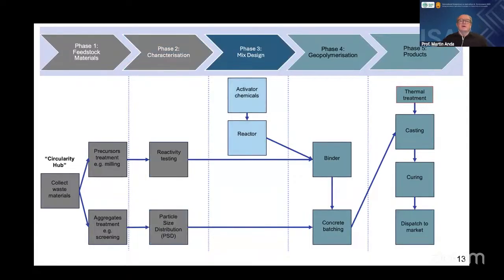Once we've done that, we can go into phase 3, which is developing the mix design, and the chemistry behind that can get quite complex. And from that, we can determine which ratios of activator chemicals, what proportions we need. Most commonly, this is sodium silicate and sodium hydroxide, and the ratios are calculated to arrive at the mix design. And then these are put in the reactor to achieve the right mix of these activator chemicals.